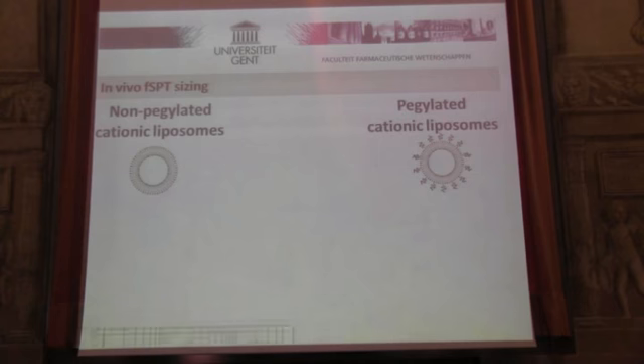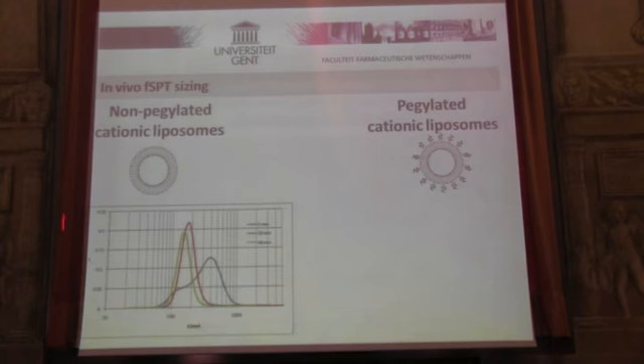So we did this more carefully. This is what happens with a non-pegylated liposome. So relative size distributions again, the rat was injected and we take a sample at 5 minutes, 20 minutes and 40 minutes. At 5 minutes, we see massive aggregation, as we expect from the artificial system. And then interestingly, as a function of time, the aggregates were actually removed from the blood circulation. So we know from this experiment, if you have aggregation, it's quickly removed from the bloodstream.